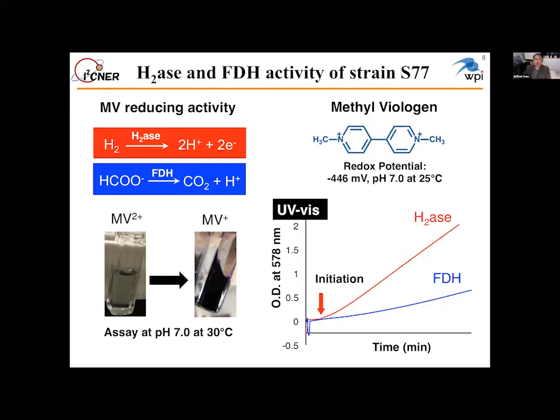One bacterium, which we call strain S77, contains two enzymes: hydrogenase and the formate oxidation enzyme, which we call formate dehydrogenase. Very rapidly they can reduce methyl viologen. This is a very low redox potential artificial electron acceptor, but we can use this system very easily. And then we compared hydrogen and formate. Hydrogenase is the more active enzyme, we found.